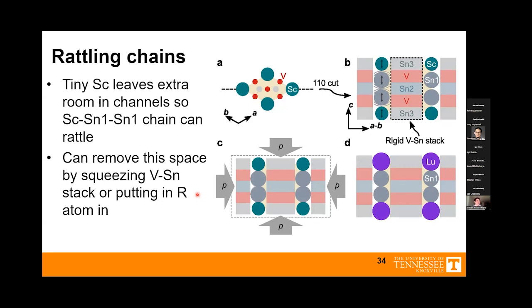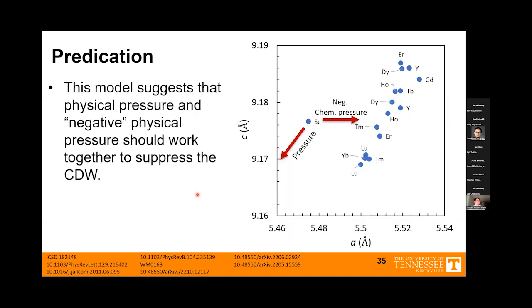And that's what we see. Pressure kills the charge density wave. Doping with bigger rare earths kills the charge density wave. But something's odd here. Generally, when we put a bigger atom in, we're thinking of negative chemical pressure. We're expanding the lattice. And when we squeeze, that's positive chemical pressure when we apply gigapascals of pressure. So something's odd here. But our rattling chain model suggests that they should have different effects.